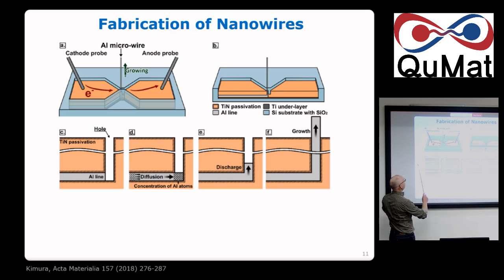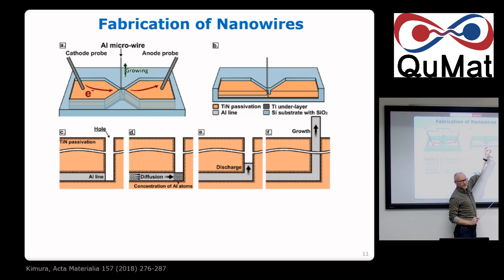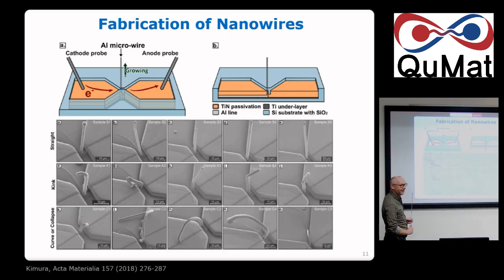Once again, we have this titanium nitride bad conductor. He made a hole here. You have an aluminum layer. This is the aluminum line. You just apply current. Current comes through the aluminum. When you reach the end, it goes to the titanium nitride. And he pushed, and you get a nanowire popping up. So this is how it looked in real life. This is nanoscopic, and then we made some theory, everything corresponds to a grain boundary and so on.